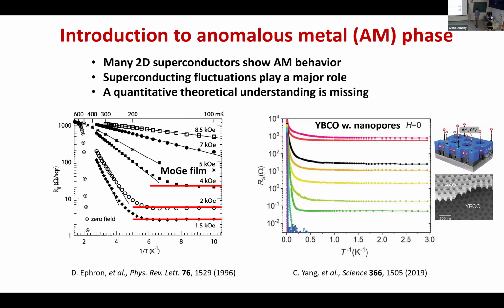And why is this strange? Because usually if we estimate the normal resistance here, if you argue that this is just because we have some region that never superconducts, and then you have some region that superconducts, then from this resistance we can estimate the size of the region that never superconducts. And the size is so small that the superconducting region should induce superconductivity in this small region via the proximity effect. So that means that even if you see some kind of small resistance, at low temperature it still should go down to zero due to the proximity effect. But this is not the case for many of these systems.